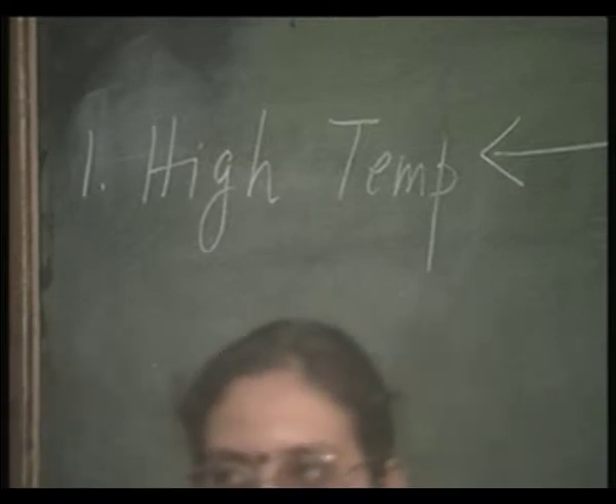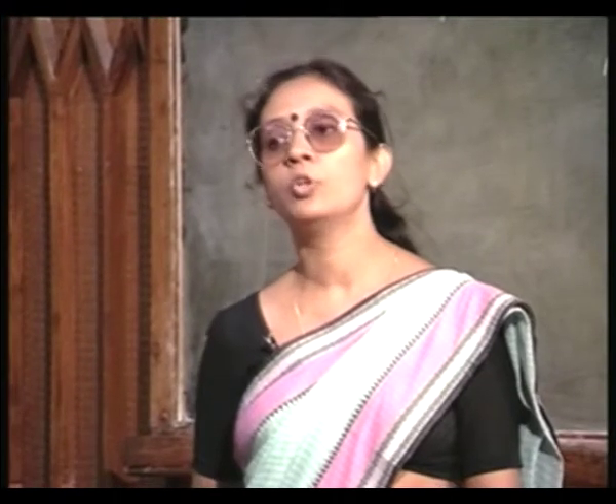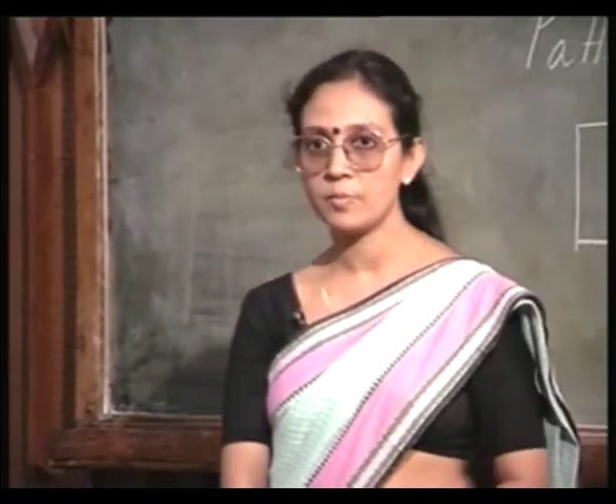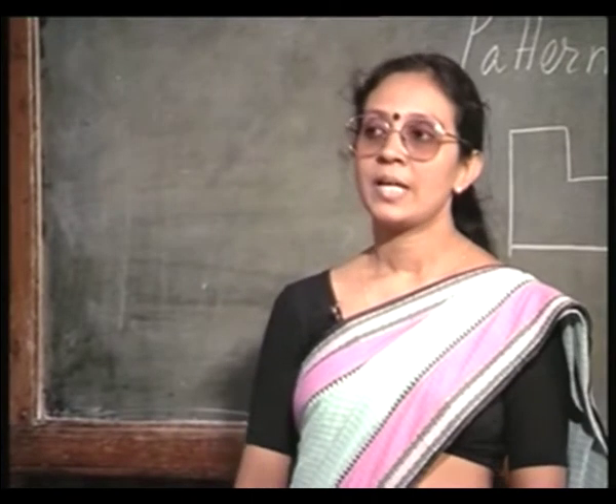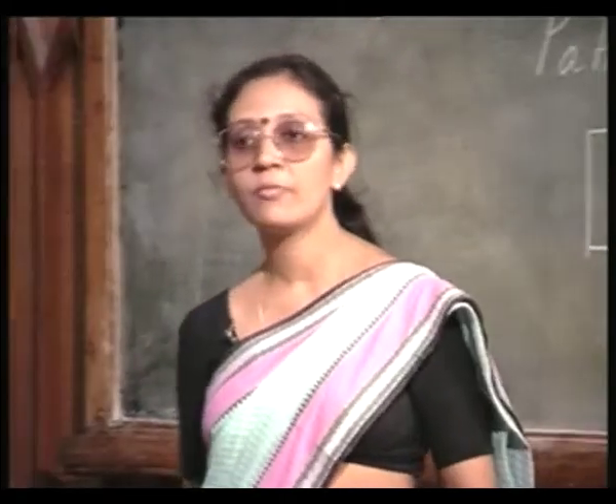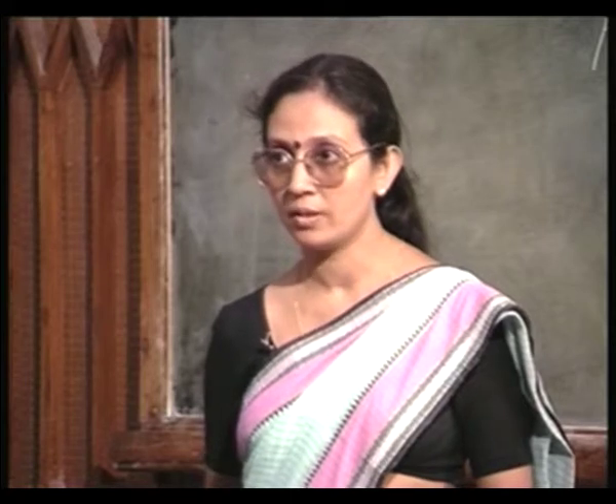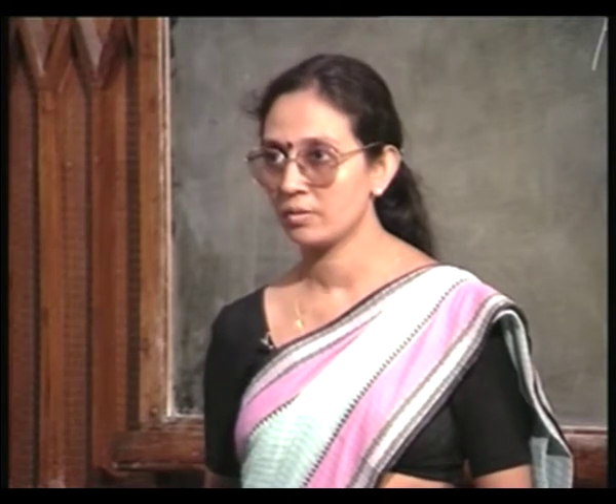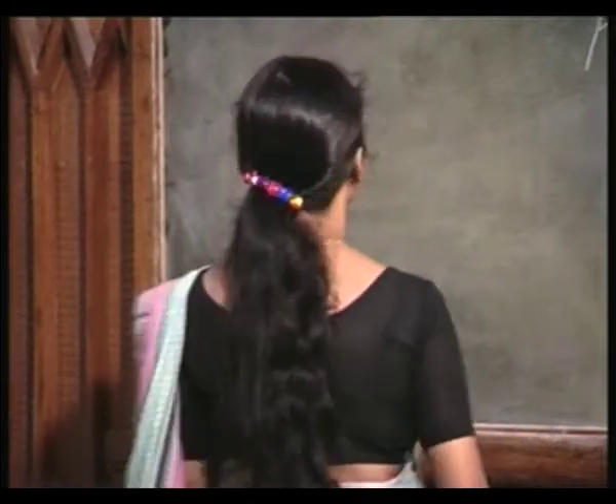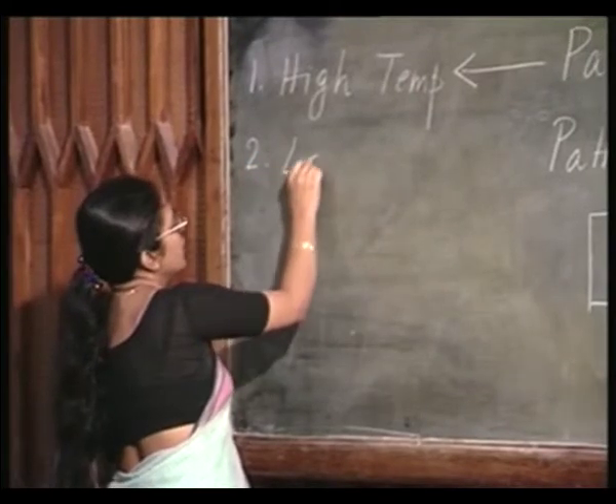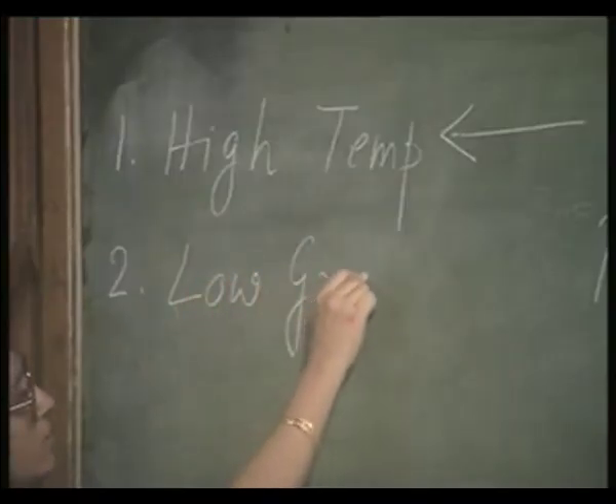Also, if I operate in the region of low growth rate, remember last class we showed a graph, that is the silicon tetrachloride concentration. As you increase the concentration of silicon tetrachloride, the growth rate increases, and if the growth rate is too high, you do not want that, because you get polycrystalline layer. So, you see, again this sort of follows as a corollary. If you have a reduced growth rate, that means the crystal quality is better, the layer quality is better. So, again the growth tends to be isotropic. Okay. So, the second point is you should operate in a low growth rate region.